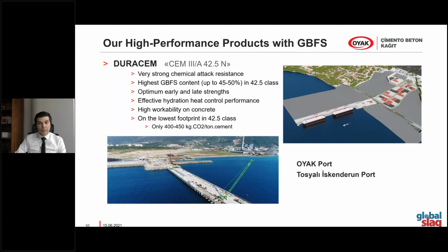The other specific products, with the increasing amount of slag, are the Duracem series. Duracem has very strong chemical attack resistance. We could reach more than 40% slag with the 42.5 class of cement type. Optimum early strength, effective hydration control, again higher workability, but one of the most important parts is also